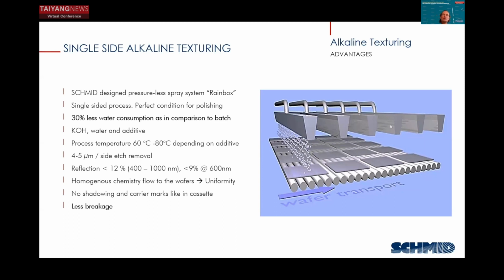It's a rain box type of system. So basically the hot chemistry is applied through a rain box on the surface of the wafers, and every rain box in a row is replacing the surface again with fresh chemistry to support very nice, very tiny textured pyramid structures. It's a single side process, leaving perfect conditions for polishing. Very important, it does use about 30% less water consumption than a batch system. Like I said, KOH water additive at temperatures between 60 and 80 degrees, depending on the additive. We remove 4 to 5 micron typically on each side. I'm sorry, on the single side.